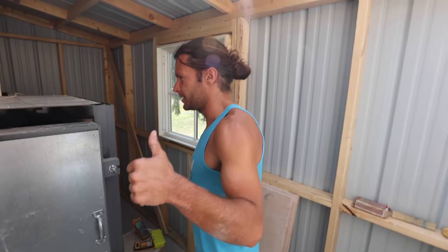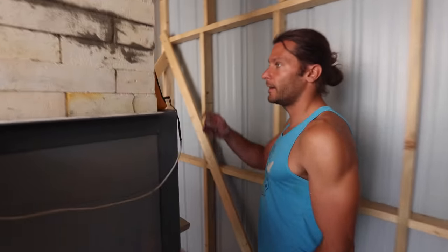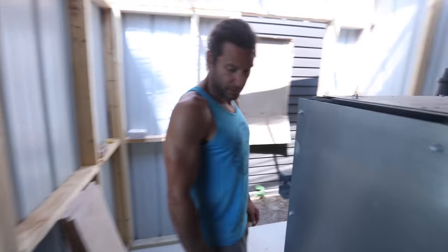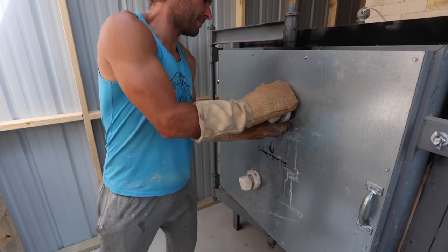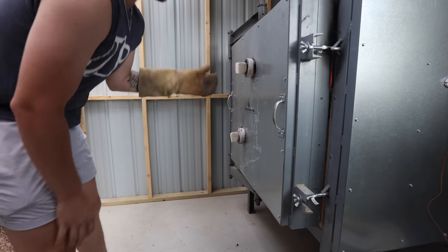It's 11 o'clock, started at 5 a.m. The pyrometer is at 2,070 — definitely not climbing quite as fast anymore. We're at 2,015 on the oxy probe side. We're checking the oxy probe, which is at 750 — that's heavy reduction, right where we want to be. It's actually pushed in a little more than it was before. Let's check the peepholes. Nothing's going to go down yet. I'm going to look in the top. I'll take a quick peek at the cones again at noon.